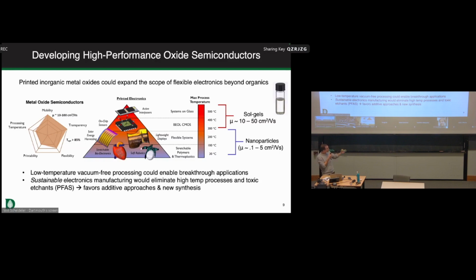Now, if you look back sort of at the last couple of decades, the best way of doing this for flexible and printed electronics was essentially two different options, two different chemistries. One of them used a sol gel chemistry, which was typically a dispersion of metal salts in a solution. And the second was to use nanoparticles. And those two methods, while they can give you relatively good performance, the challenge is that they also require higher temperatures. So higher temperatures translates to essentially a larger embodied energy for whatever device or material you're making. So there's an environmental impact to it.